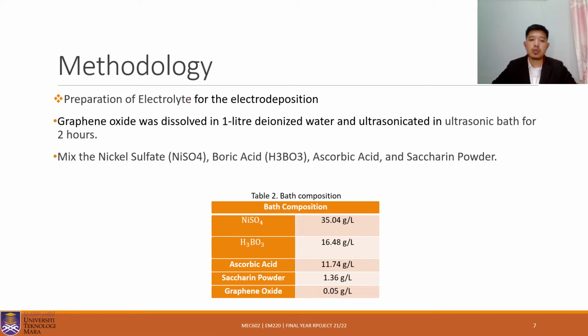Next is preparation of the electrolyte for the electrode deposition. Graphene oxide was dissolved in 1 liter deionized water and ultrasonicated in an ultrasonic bath for 2 hours, then mixed with nickel sulfate, boric acid, ascorbic acid and saccharin powder. Table 2 shows the bath composition.